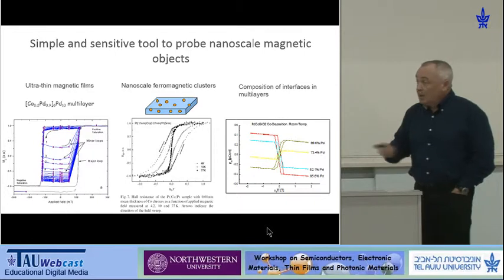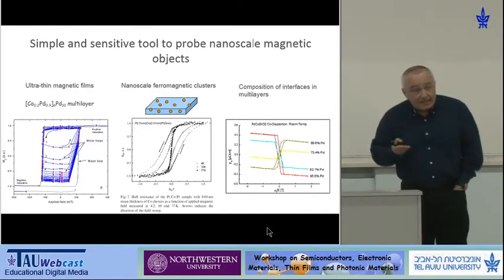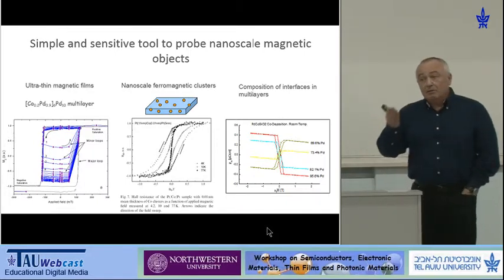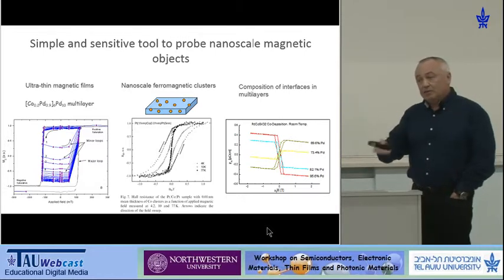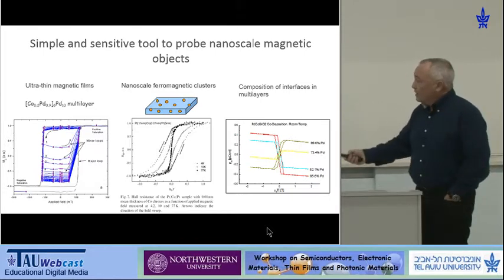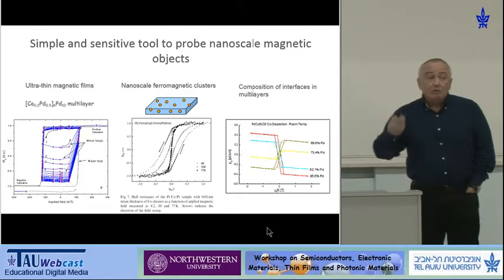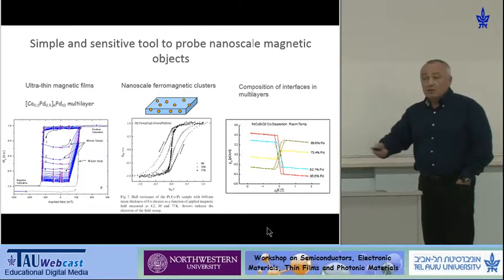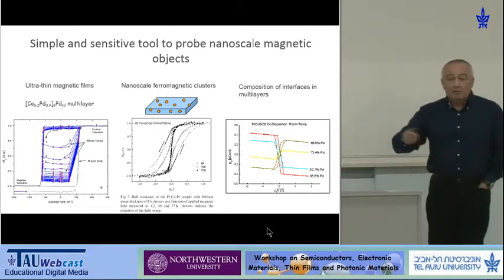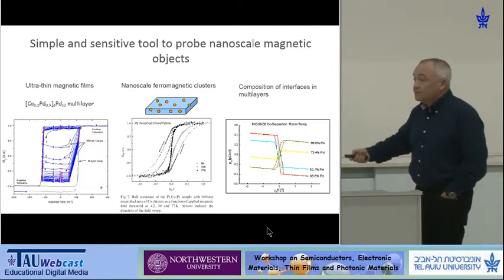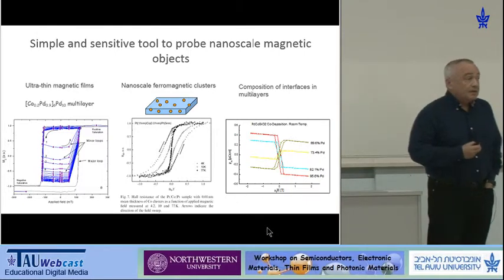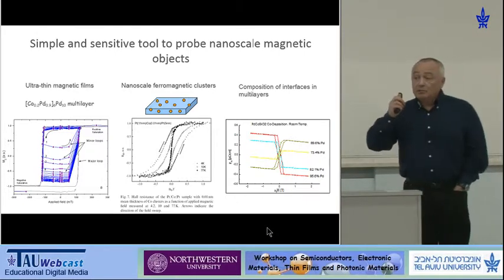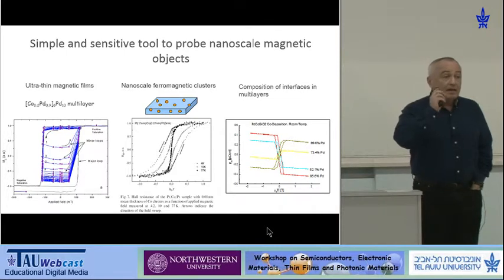But if our material is still conducting, all the magnetic response comes through conduction, through the signal generated within the material itself. We do not measure the substrate. That's why it appears to be remarkably sensitive to measure all the possible things in very thin magnetic films: hysteresis, relaxation, whatever. Now, if the film is non-conducting, if we talk about, let's say, finite clusters of the material,